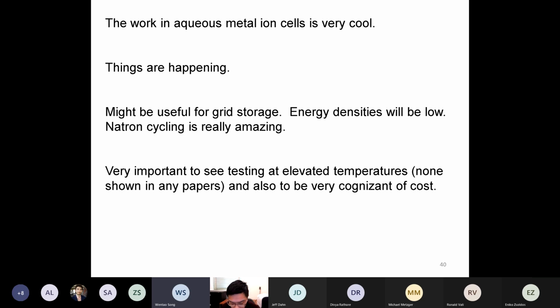That's a very good comment. If we want to study that more, we should invest more energy and time on that. But the thing is, it's very hard to measure these small structures because they won't show any signal by X-ray diffraction or scattering. The only thing sensitive to water or lithium is neutron. So the only way we can measure the scale of these domains is by neutron scattering.